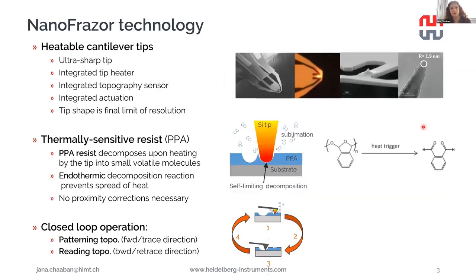So when can we use the NanoFrazor? We can use it whenever we need to artificially make nanostructures on the surface. The key concept here is to use a heatable cantilever tip for nano patterning features on a thermally responsive resist. Whenever this cantilever tip touches the surface, the resist is immediately sublimated, and this happens on a microsecond scale. The reaction in this case is also endothermic, so it does not heat up the substrate, and it's also non-invasive.